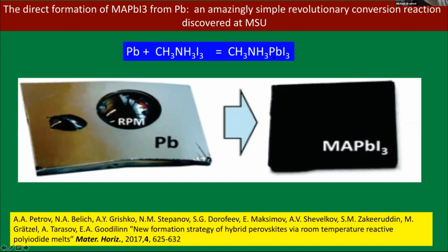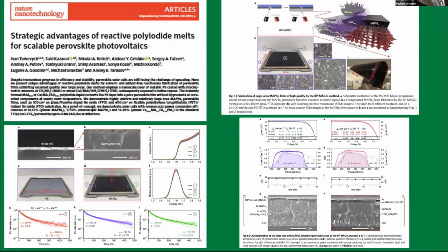So that was a very elegant strategy, and it was published first in Materials Horizons, but more recently the paper appeared in Nature Nanotechnology, which gives you really the gist of how these systems are produced. But you can see right away here the lead is a 60 nanometer thick film, and it turns into 500 nanometer thick lead perovskite. So the volume expansion is huge, because the density is much lower for the methylammonium lead iodide than for lead. But the films behave well, and very reasonable values for efficiencies were obtained.